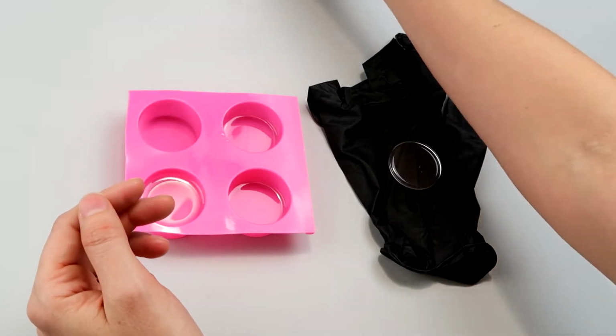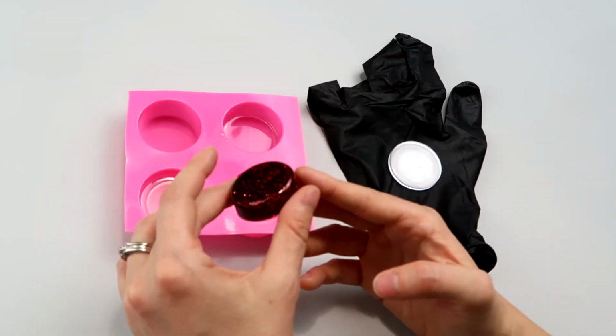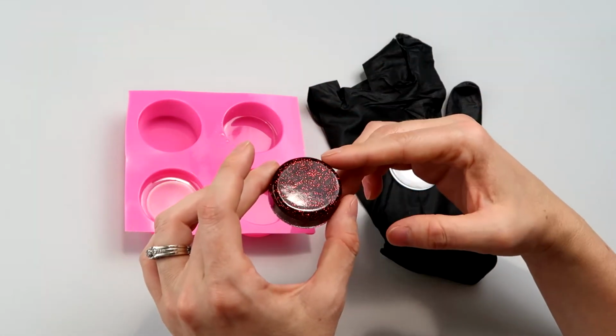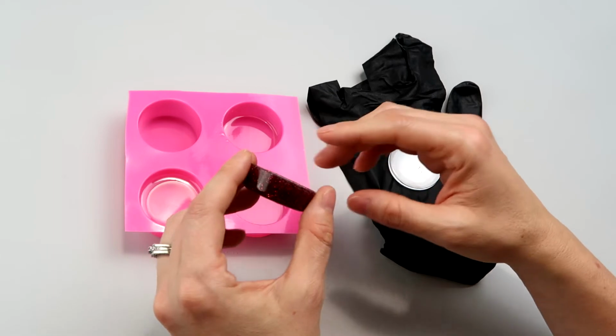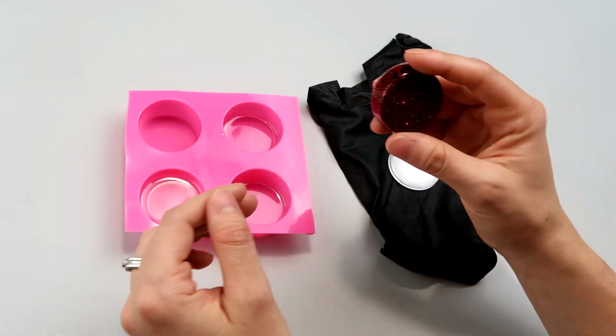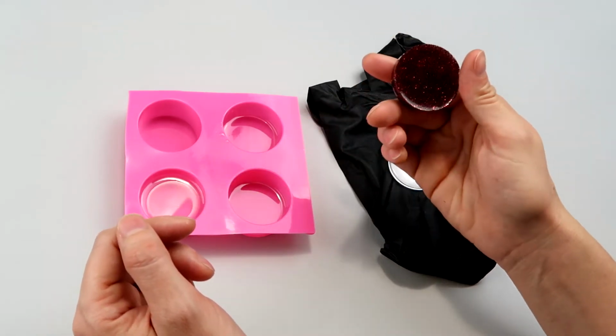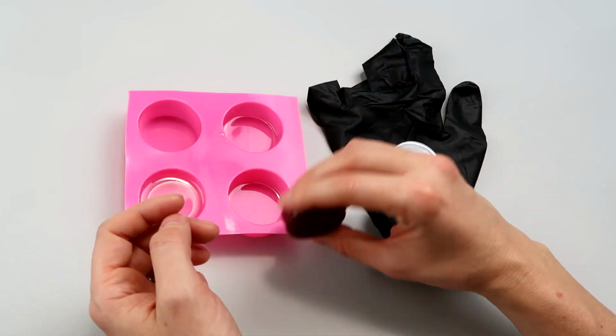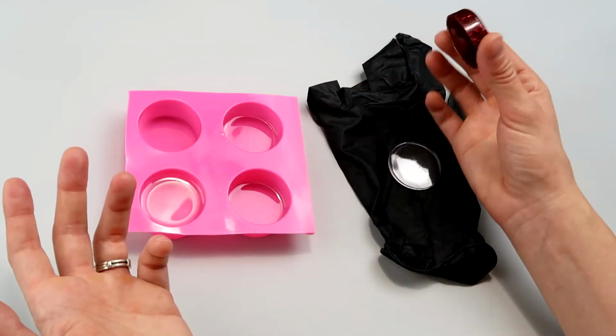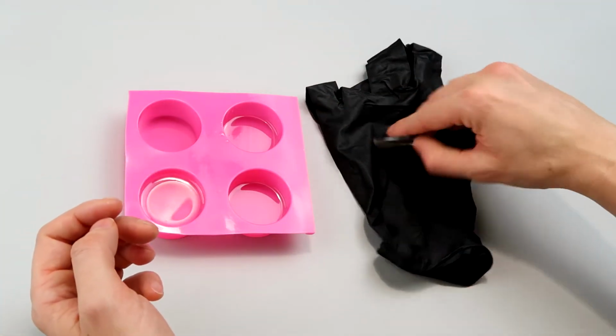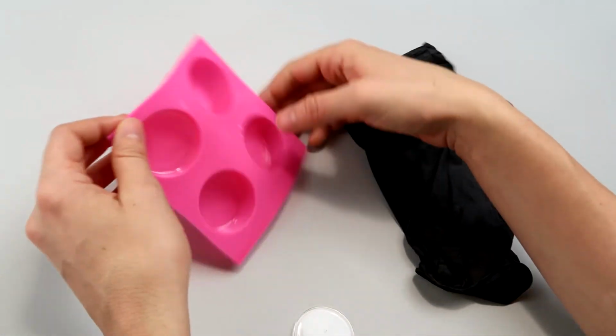And I do have to say that when I was testing the pot life and mixing up the resin with the glitter, when I didn't heat up the resin and just mixed it, there were so many bubbles. There was just an absurd amount of bubbles. So if you don't heat it up, that's a problem you're gonna run into. So there's that one.